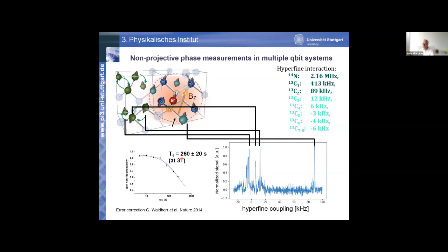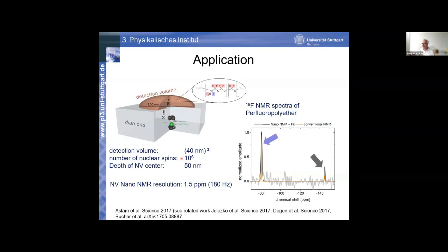So if you employ this quantum memory trick and this entangled, disentangled type of correlation experiment, you really gain massively in spectral resolution. And we were showing this, it's almost now 6 years ago. So we were taking a single electron spin together with a quantum memory. We were measuring the NMR signal, so the Larmor oscillation of different nuclear spins in this molecule. It's a perfluoropolyether. The important thing is that we use the fluorine nuclear spins, which actually have 2 different frequencies. Although all of this is fluorine, this pinkish guy here has a different frequency than the other ones because of the chemical shift.